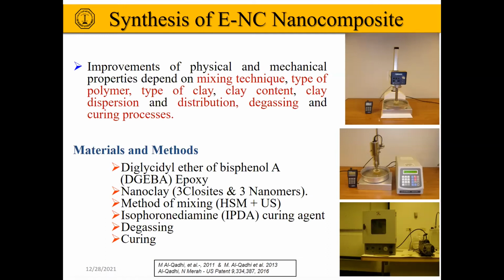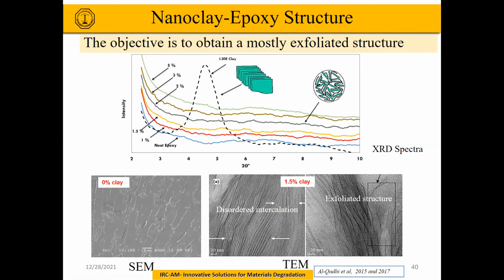So we looked at different mixing techniques. We looked at different clays, different ways of making this, and actually we ended up with 2 patents for ending up with an exfoliated structure that you can see here. We were able to get mainly disordered intercalation and exfoliated structure every time we went through the process that we have designed. And the exfoliated structure is what we want. The objective is to obtain a mostly exfoliated structure.